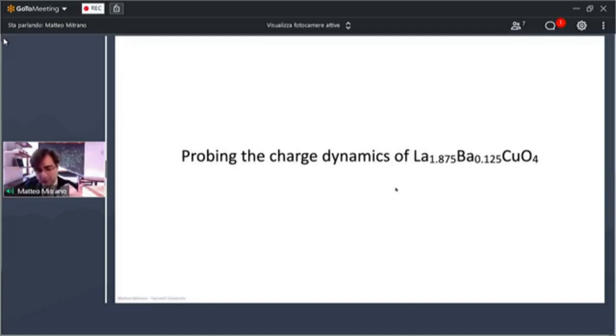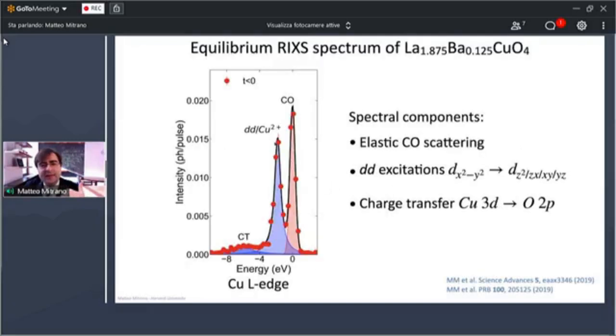So what we did is that, during my postdoc, I've been able to perform the first time-resolved RIXS measurements on this material. And we decided to investigate the charge dynamics of lanthanum barium copper oxide following laser excitation that brings this enhancement of the c-axis tunneling. And this is the first RIXS spectrum taken on this material at an FEL.